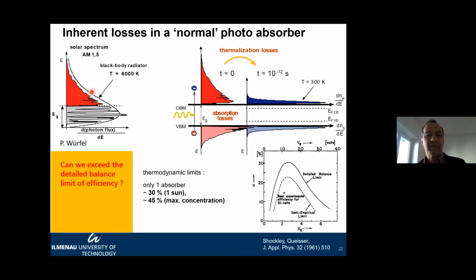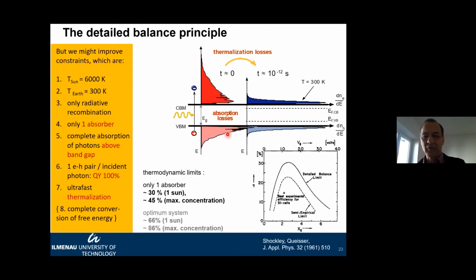And these two huge loss channels already, together with a few more, like, for example, Auger recombination, lead to this limit that a normal photoabsorber can never produce higher efficiencies than around 30%. And the question is, can we change this? Is this wrong? The brief answer is no, it cannot be changed since it's a physical limit. However, what can we change? We can change the boundary conditions of this limit. And this you can see here.